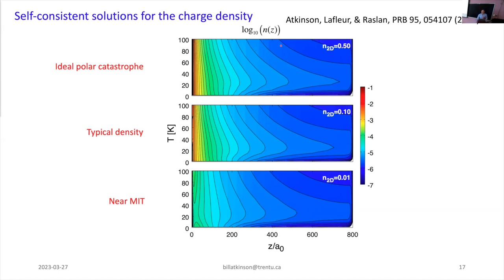And I've got three electron densities. So this top panel, N2D is 0.5. That means I have a half electron per 2D unit cell. So that means that if I integrate my charge density from the interface to the back wall, I get a half electron per 4 angstrom by 4 angstrom unit cell. Okay, so that half electron is the ideal polar catastrophe value. That's what you would expect to get.